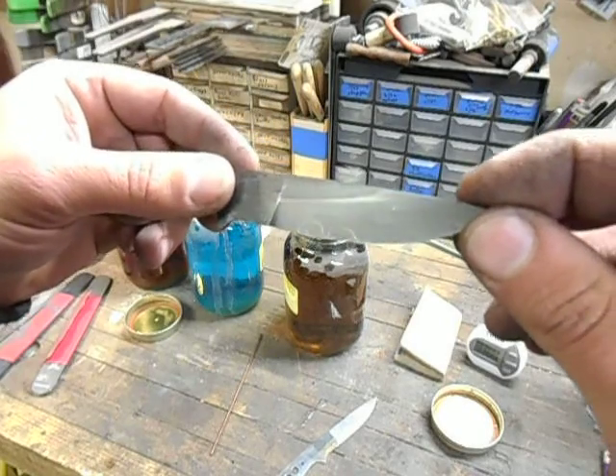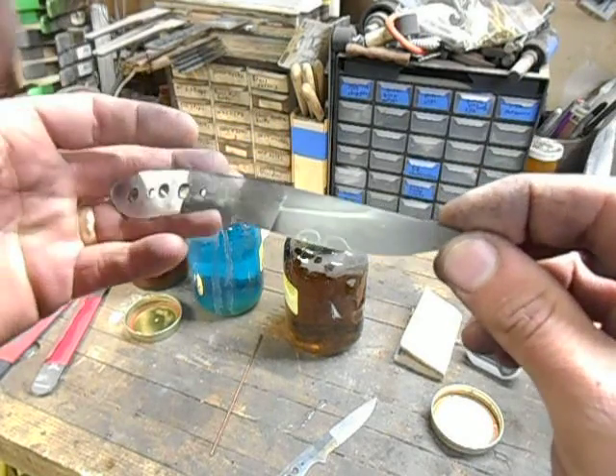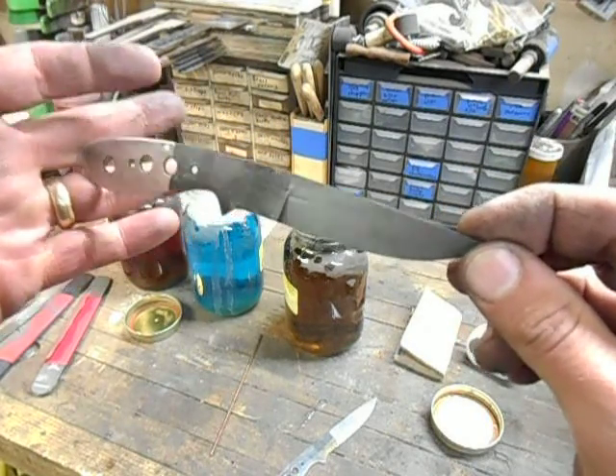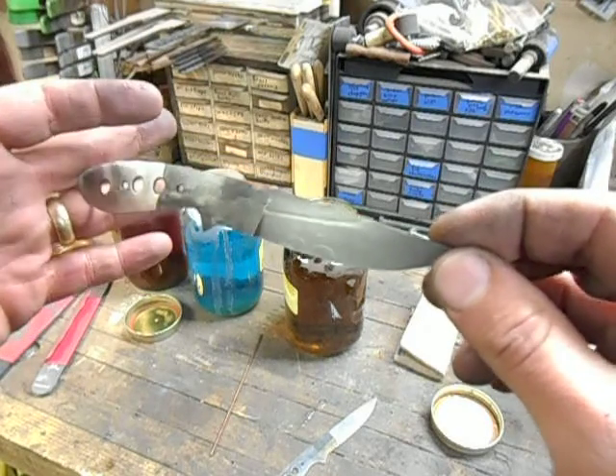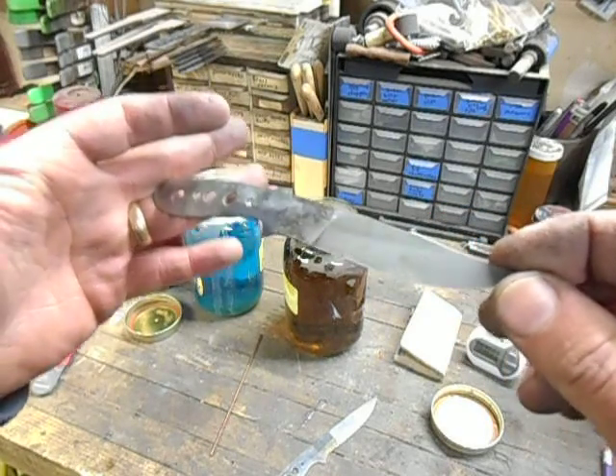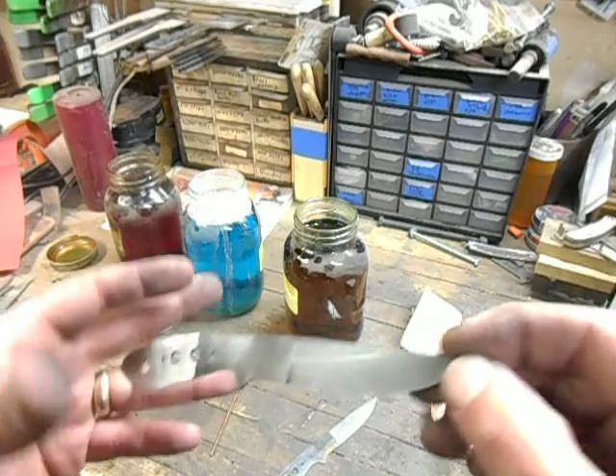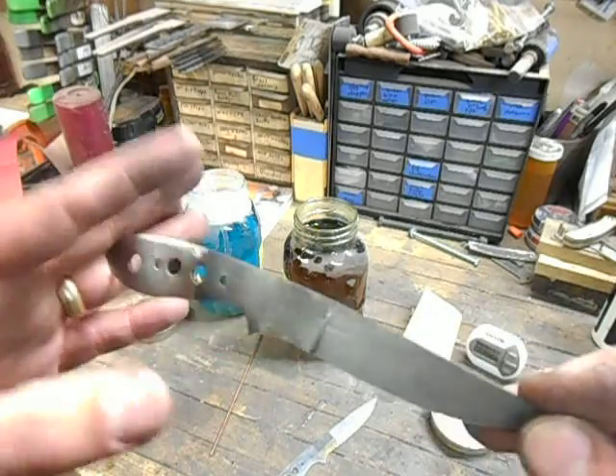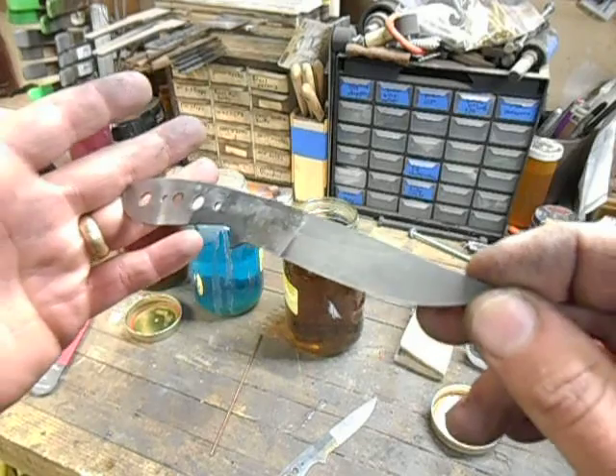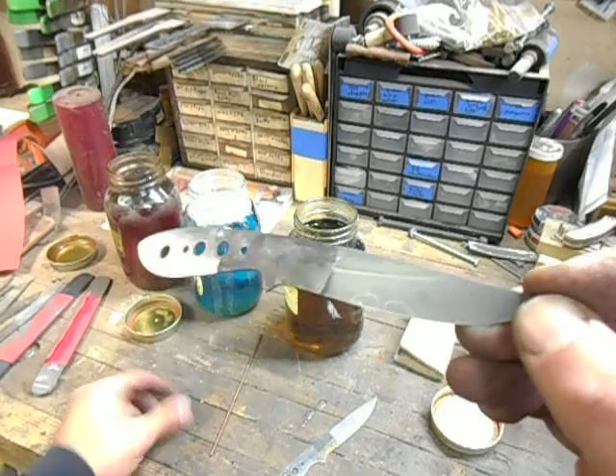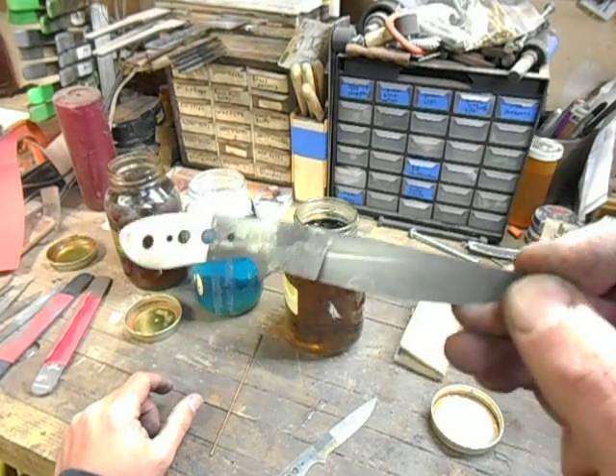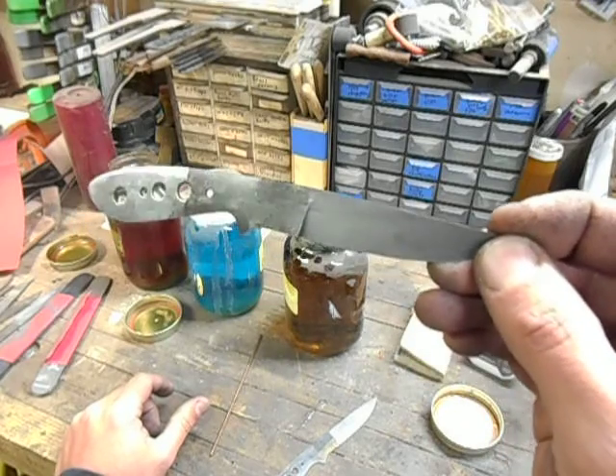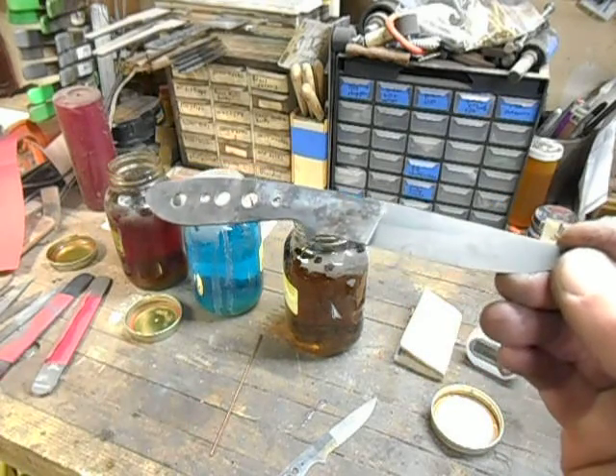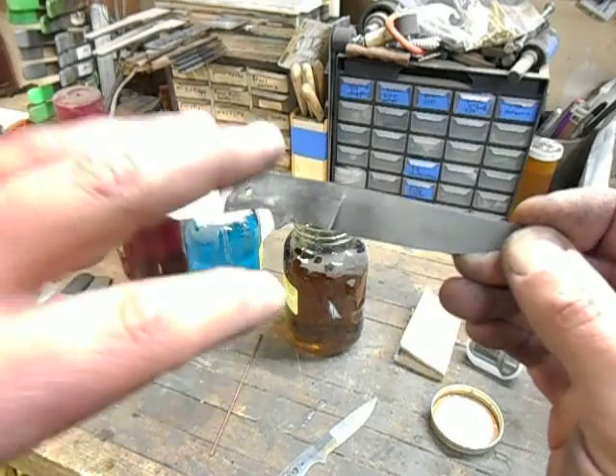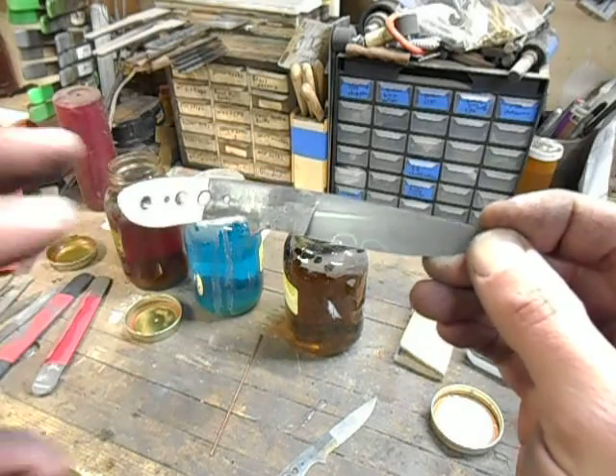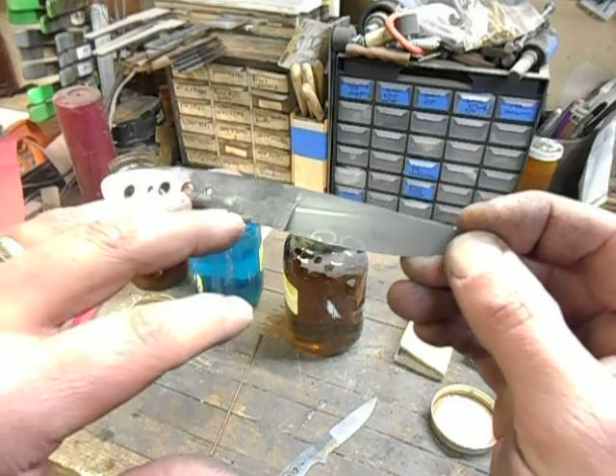But anyway, that's just a quick and dirty 400 grit hand sanded blade, dipped in ferric for 7 minutes at 1 to 4, one part ferric to 4 parts distilled water, neutralized in TSP solution, and rinsed off right quick. They look an awful lot nicer when you shine them up, but this is the basics, and not only the basics of how you do an etch, but also the basics of what it is that you're looking for when you etch a blade.